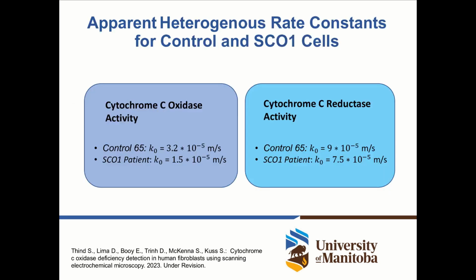So let's come back to our cytochrome C oxidase active cells. Our control cells here exhibit a kinetics of 3.2 times 10 to the power of -5 meters per second. And you can see that our patient cells have a reduced cytochrome C oxidase activity by almost half. We can also analyze the cytochrome C reductase. Although this has not been altered in these organisms, we can still see a trend that here also the reductase is slightly decreased.